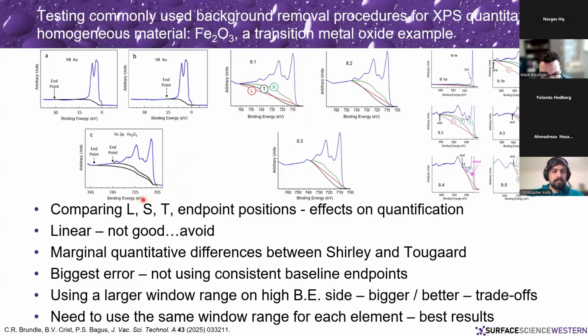What they found is that, especially if you're comparing materials, you needed to use the same background endpoints to make comparisons useful, to even get semi-quantitative data that really mimics what you have. So if you have so much iron versus so much oxygen, there should be a certain ratio if you believe you have Fe3O4 or Fe2O3, or even if there are other species present. The ratios in your survey spectra should follow stoichiometry reasonably well if you're doing this quantification right. Again, there were very marginal differences between the Shirley and the two-guard background. The positioning of those endpoints is what mattered more than anything. And so you need to think about that when you're doing your analysis.